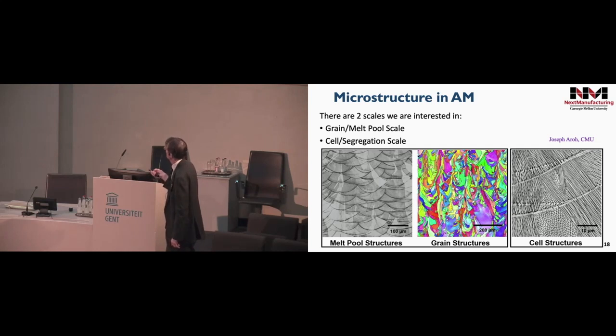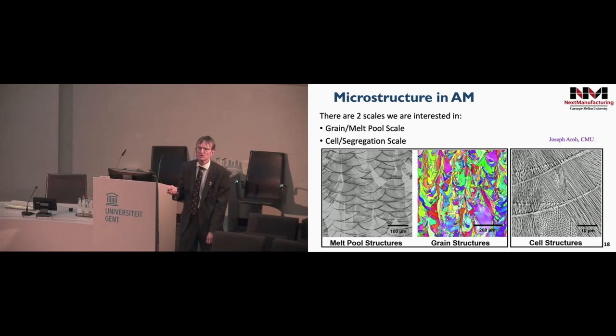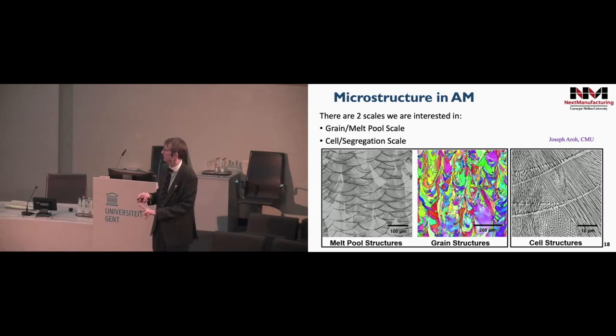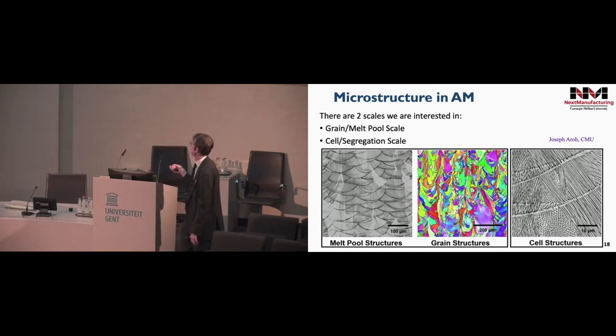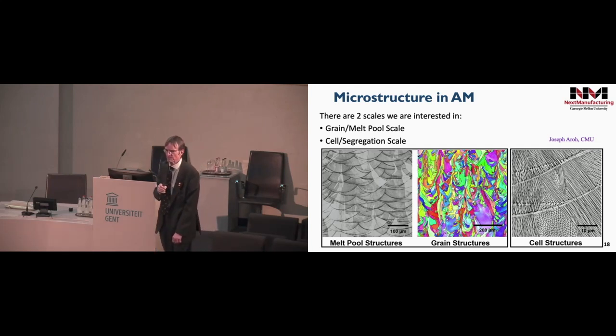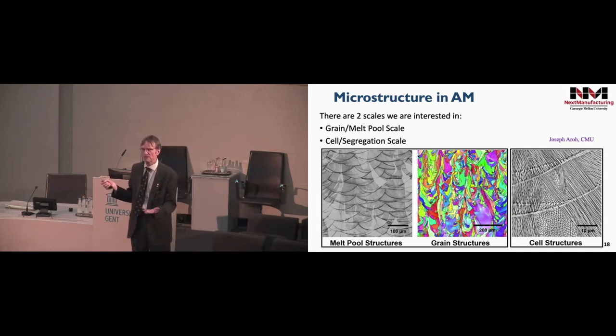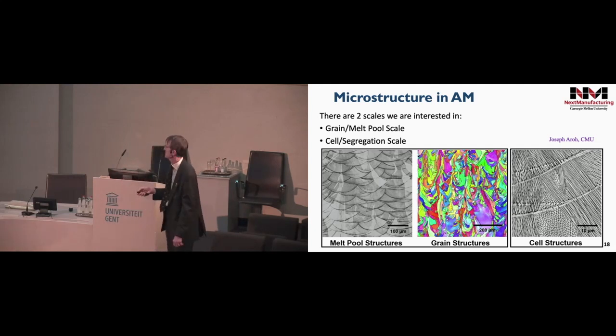To the right of it in the center is the sort of grain structure that you might expect to see in a stainless steel or a nickel alloy. And I draw your attention to two things at least. One is that there are long, skinny grains growing up through the microstructure, but there are also grains that look fairly equiaxed. So we have some work to do to explain how those microstructures come about. Okay, that I think I can actually help with.